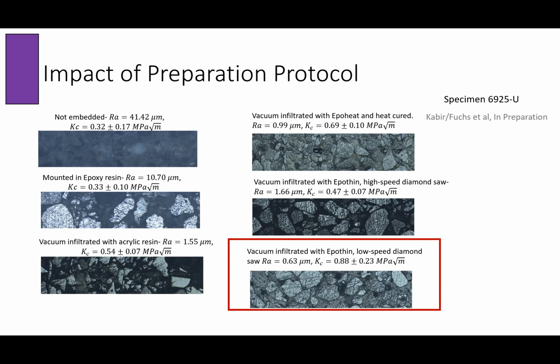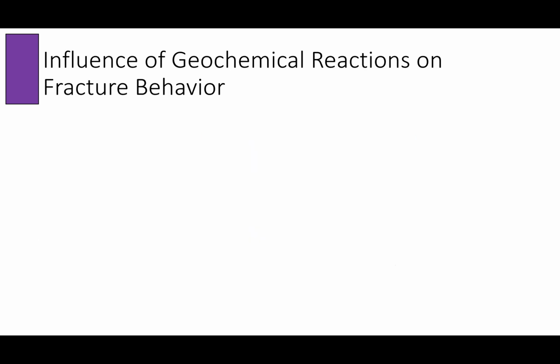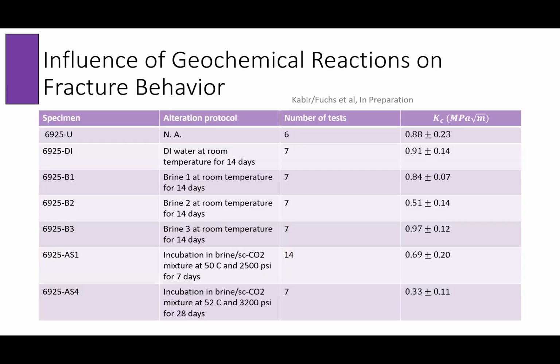Now, this is also a little bit challenging because, as we're going to see, when you have this aging process in CO2 saturated brine, one of the issues that is occurring is just the increase of the roughness of the sample itself. So again, the preparation process is actually very important, and it takes several months to be able to derive it. So then let's look at the fracture behavior once we have that preparation protocol.